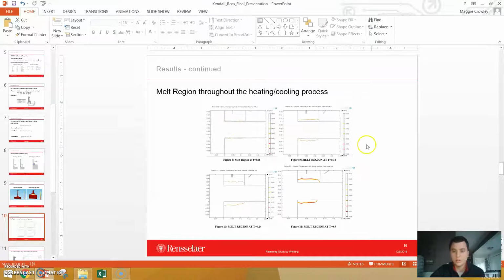And then I changed the temperature regions for the contour plot to just be those during the melting phase of stainless steel. So all this little band here is the melting region of the stainless steel. As you can see, as time moves forward, that melting region extends out further into the stud and into the target plate. And then once that's removed, this thing starts to cool down.